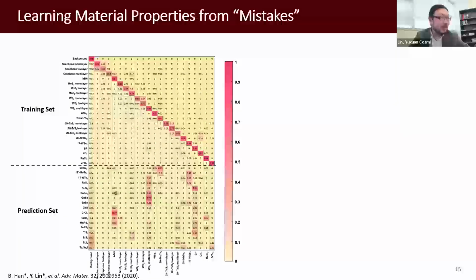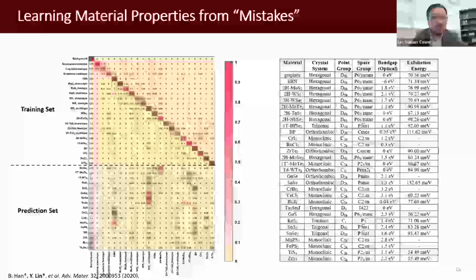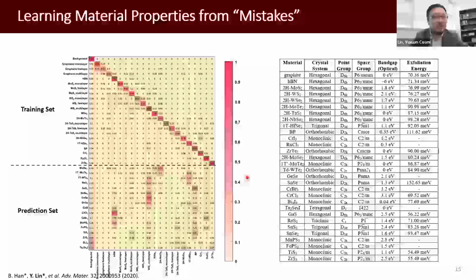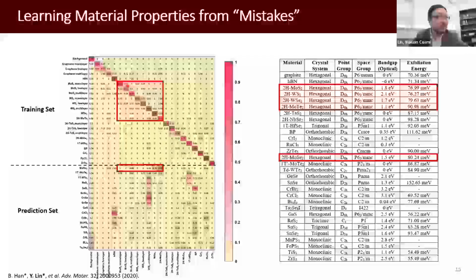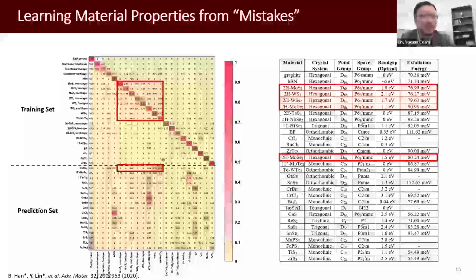We also feed in additional materials we didn't use during training, so we can extend this matrix. All the mistakes the model is making are actually related to the similarity between the two materials. So here are all the materials and their properties. Let me highlight some of them. For this square, they are all TMD 2H phase semiconductor materials, and in the prediction set, we use another material. So you can see they have this similarity.